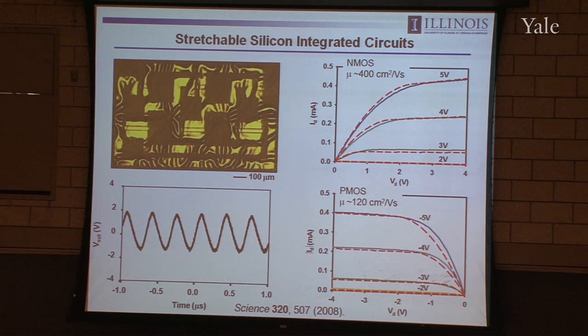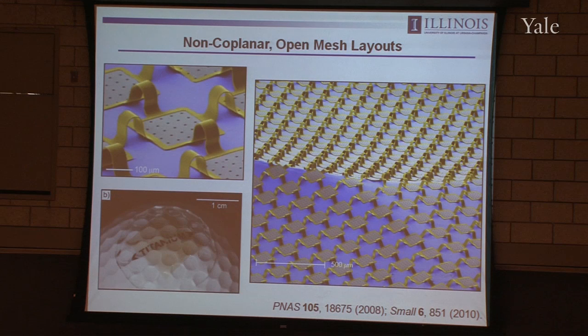And the way that you can do that involves two steps. One is taking the circuit and etching away parts of the material in the substrate you don't really need. There's no device there, there's no device there. You can just etch that into an open hole so that the circuit takes on the layout of an open mesh. And furthermore, you design specifically which part of that mesh bonds with the underlying rubber substrate. Not everything should bond if you want to optimize the system, just selected locations. You can do that by tailoring in a patterned way the surface chemistry. And if you do those two things, then you can make systems that look more like this. So this is just a test platform.